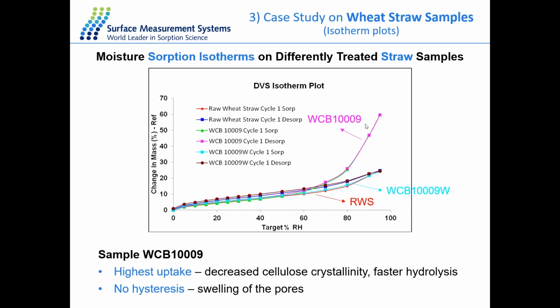And you can also notice that there is no hysteresis gap between the sorption and desorption isotherm for this kind of material. And this is due to the swelling of the pores inside the material, resulting in less capillary force for the water diffusion. And this means the water molecules can travel freely between the bulk and the surface in the case of this treated straw sample.